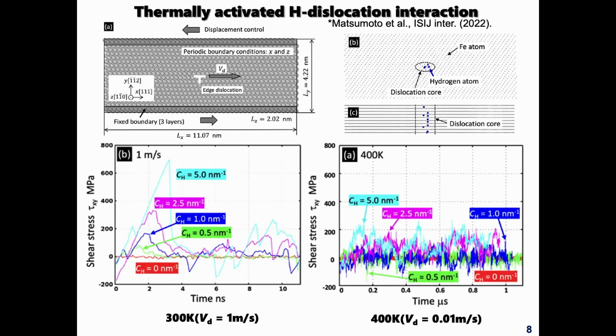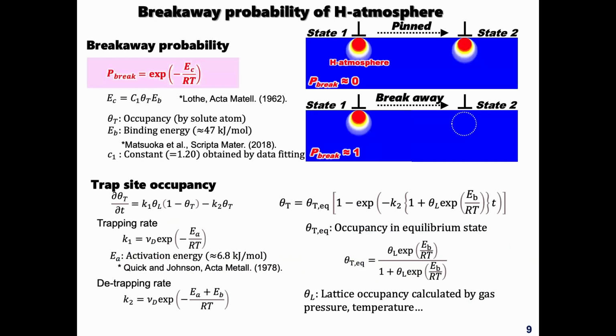But at higher temperature, 400 Kelvin, the shear stress to overcome it is much, much lower than the 300 Kelvins, and especially in the lower dislocation velocities. So this result indicates the higher temperature with lower loading frequencies generates the lower magnitude of the accelerations. So now we try to discuss the overall hydrogen-assisted fatigue crack growth aspects from the viewpoint of the breakaway events of dislocation from hydrogen atmosphere.